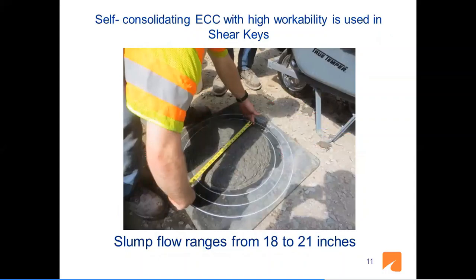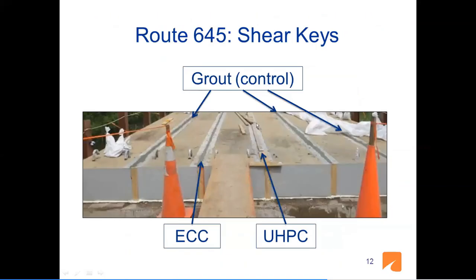As you see, the way the ECC is prepared, you make a very highly workable mortar, and then you add the fibers into this mortar. And at the end, you end up with a self-consolidating concrete. This is now the mortar mixture with the fibers in it. And the slump usually ranges from 18 to 21 inches. So this is what we use in shear keys. In that bridge that I showed you, we used the basic grout mixture that they have been using.